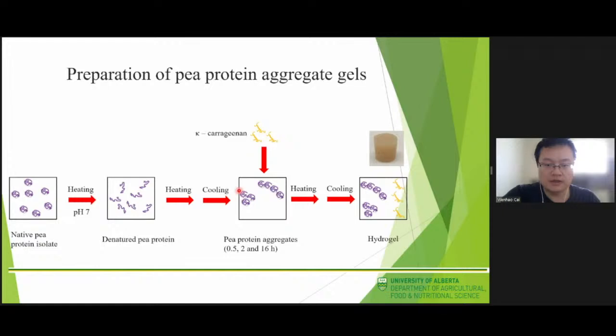Then a low concentration of 0.5% κ-carrageenan was dispersed in the pea protein aggregate suspension, and it significantly improved the pea protein gel mechanical properties. In addition, this relatively low κ-carrageenan content would not significantly decrease the protein content in the gel formulation, as a protein claim is favorable for industrial applications. This also avoids the gummy texture brought by polysaccharides in the final product.